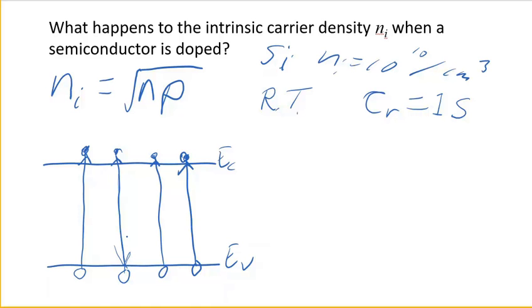In this case, every quarter of a second, something gives. But it has to maintain thermal equilibrium. It has to maintain this condition. Meaning, for every electron that returns to the valence band, another one has to come back. And so another hole, an electron, is created. So if every quarter of a second an electron goes back to the valence band, every quarter of a second, an electron is promoted to the conduction band, leaving behind a hole. So that you maintain this thermal equilibrium statement. That gets maintained.